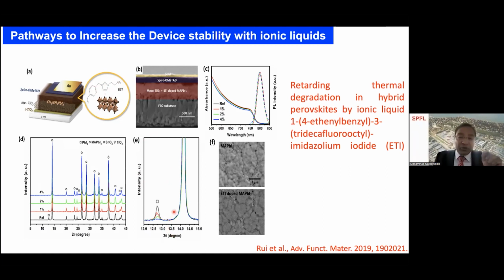So what happens if you use a perovskite without this ionic liquid? You can see the presence of lead iodide. The presence of lead iodide is an indication of instability of these materials. Now, if we use 1%, you can see it's decreasing significantly, and 2% is a further decrease. Let's say if you take 4%, there is no formation of lead iodide, showing that with the presence of this ionic liquid to the extent of 4%, you can make it extremely stable, so that you don't see the formation of lead iodide. The rest of the characteristic features are the same, like absorption spectra, emission, and surface images.